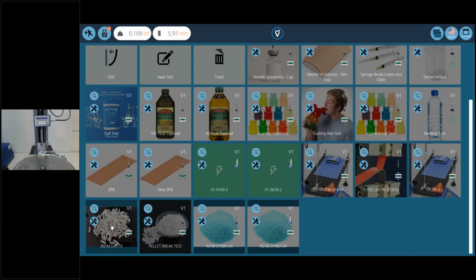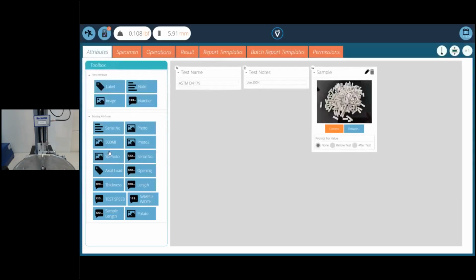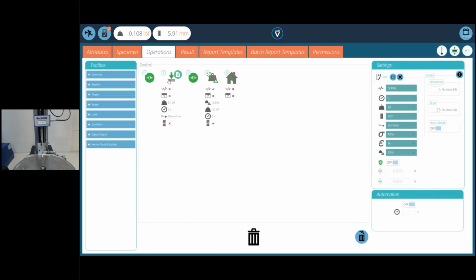Now, the test that we've written is kind of loosely based on the testing standard. However, we do capture all of the essential parts of it. Again, for purposes of time and this presentation, we've kind of abridged things a little bit. So all the test is doing here is going to ASTM D4179. And again, in the testing operations, all we're asking it to do is zero, run to a preload, and then apply. The standard calls for between 1 and 10 pounds per second. We've chosen to apply 2 pounds per second for purposes of our demo until the test completes. And we're going to run this to a maximum of 20 pounds or break, whichever happens first. So as you're applying 2 pounds per second, your target load is 20 pounds or break, whichever comes first.